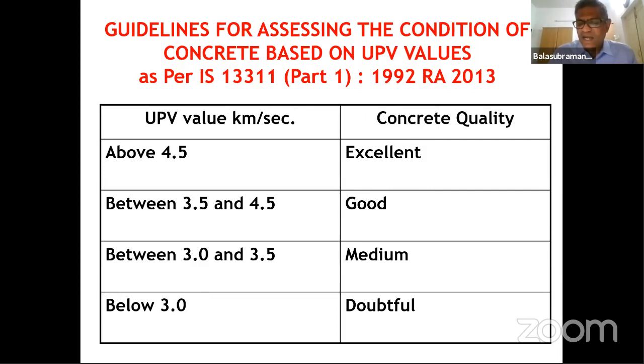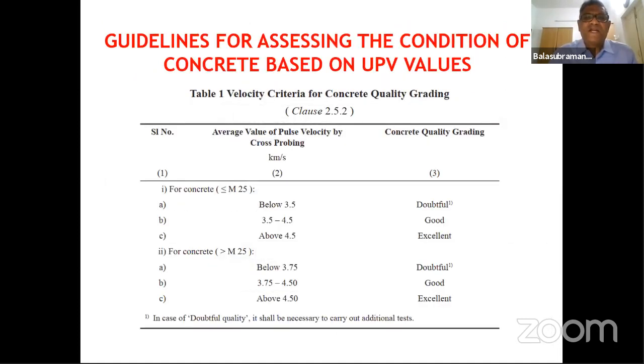Now the recent IS 516 Part 5 has come out with this kind of specification. They say that for any grade of concrete less than M25, any velocity below 3.5 is doubtful, 3.5 to 4.5 is good, above 4.5 is excellent. And for all grades of concrete above M25, it says below 3.75 is doubtful.